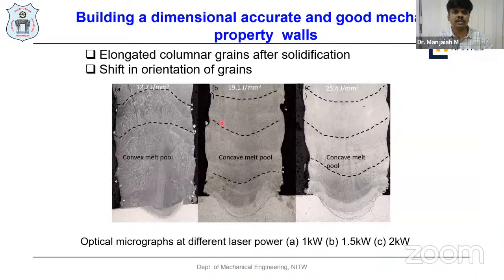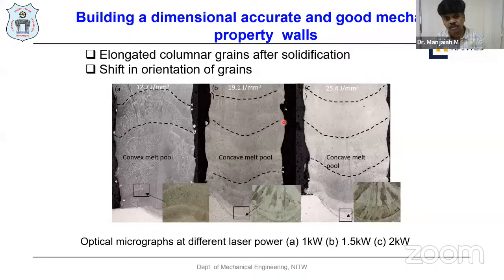And if you see the other dimensional errors we have got in the fabrication process with the different laser powers, you can see elongated columnar grains can be visualized. These kinds of convex, concave, and multiple profiles are formed because of the shift in the orientation of the planes, and even with the bottom structures, because the energy density is not sufficient to melt or remelt the previous layer.